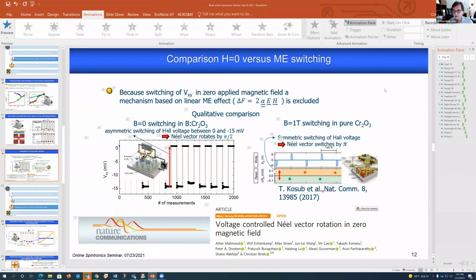So let me speak for chromia. That's easier. The answer is a little bit trickier. I always tell you that it takes a product of electric and magnetic field to switch the antiferromagnetic order parameter. And that is true for bulk and film, as long as you can ignore what happens at the interface energetically. If the interface plays an ever-increasing role when you make the film thinner and thinner, then it's no longer that simple that it's just the product of the two. Then there are additional energy terms that change that a little bit.